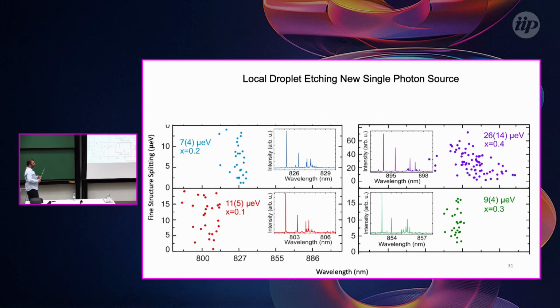With this, by changing the indium concentration inside the nano holes, I managed to extend the emission wavelength to around, let's say, 900. This is 895, but I can also find quantum dots at 920 nanometers. What is the advantage compared to Stranski-Krastanov? It's very easy to get a smaller fine structure splitting, and in this field, people are trying to do quantum memory using cesium atoms. Cesium has two transitions: one at 895 nanometers, which it's possible to use also with Stranski-Krastanov, and another that I don't remember, 852 or 854, which was blocked before with indium arsenide quantum dots because of the wetting layer in Stranski-Krastanov. With local droplet etching, we no longer have this wetting layer.